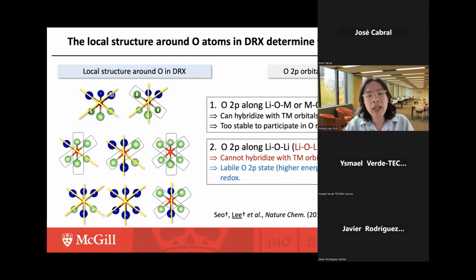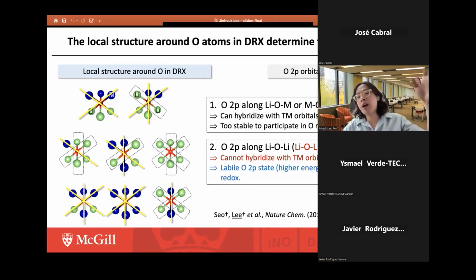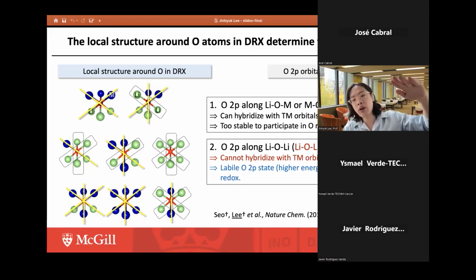oxygen 2p orbitals lying along this particular lithium to oxygen to lithium direction, which we name the lithium-oxygen-lithium state. And because the energy of the lithium state is too high, basically they do not hybridize with the oxygen 2p orbital. Because of the lack of hybridization, the oxygen 2p orbital's energy becomes higher compared to this hybridized oxygen 2p state. So they become more chemically labile. They become more ready to engage in electron extraction from the oxygen. So I hope you understand so far.